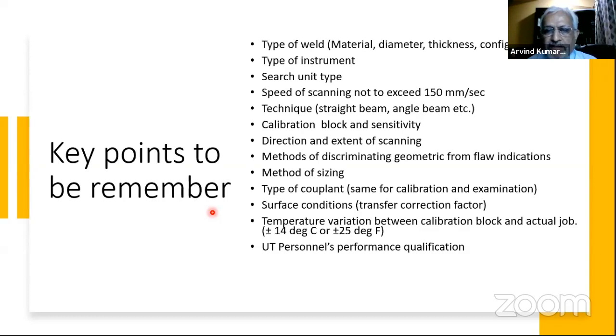Surface conditions and transfer correction. I explained that because the surface of the calibration block is different and the job is different, we have to have a correction for that. Again, this is very important: temperature variation, which people try to ignore and are not aware of, but the results may vary if you don't give importance to this.